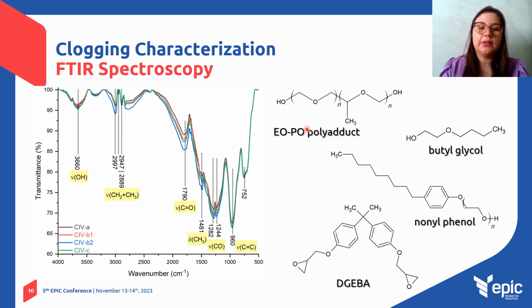that is ethylene oxide, propylene oxide polyadduct containing as preservative diglycidyl ether, bisphenol A, and nonylphenol. And this could indicate to us that these components are adhered to the surface of the clogging material samples.